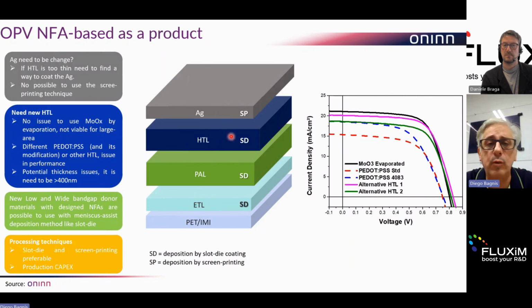And just to remember that we're speaking about layers that are a few nanometers, a few hundred nanometers. And so it's clear that there is the issue of the HTL. If you try to use molybdenum oxide by evaporation, we're speaking about a few tens of nanometers. And using this technique creates cracks and creates shunts. So in some way, it's not possible to use a thinner HTL.